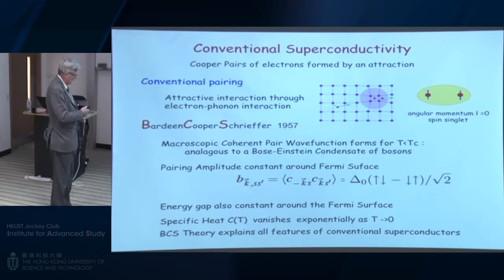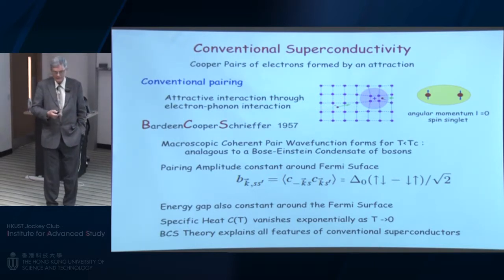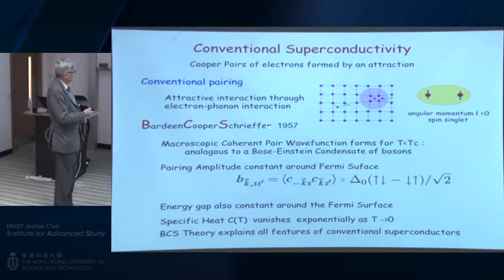The paper of Bardeen, Cooper, and Schrieffer was a remarkable achievement. In one paper, they turned superconductivity from the greatest unsolved puzzle in condensed matter physics into, it's no exaggeration to say, the best understood phenomenon. And the idea was that at low energies, the exchange of phonons could form an attractive interaction. And if you had an attractive interaction, the sharp Fermi surface distribution that I showed you was unstable against pairing.